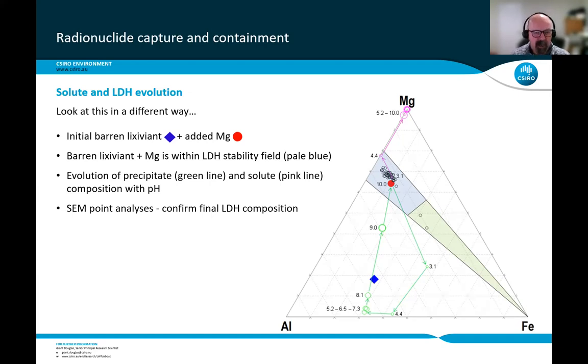So what happens when we start adding hydroxide? Well, if we start at that red point and we follow the green line around, as we start adding hydroxide, we get to pH 3.1. And so the composition of that precipitate, as I talked about before, is iron rich. So we move towards that iron apex. As we start then increasing the pH again, we get down to 4.4 and then 5.2 up to 7.3. We're starting to add Al into that. So we then start to move from towards the iron towards the alumina apex. So now we've got an iron and alumina precipitate.